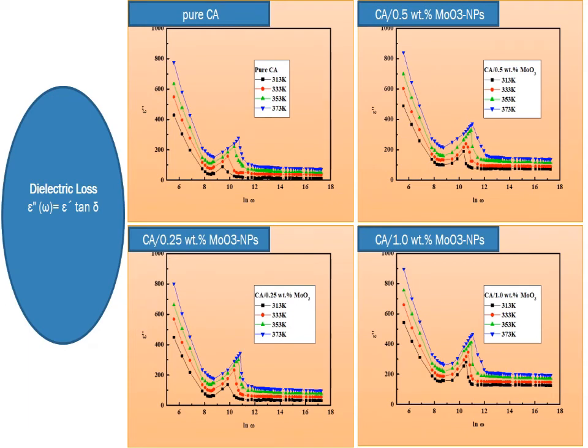By calculating the dielectric loss from this equation, we can draw the dielectric loss as a function of temperature and frequency, and we can see that there is a relaxation peak which is shifted with temperature to higher frequency. This peak means there is a relaxation process in the material.